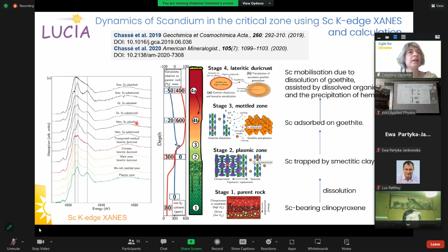And they also used calculation of XANES, for example, in this case of scandium linked to goethite, to really decipher if scandium is adsorbed or introduced into the goethite structure. That would have some consequences on the scandium availability.